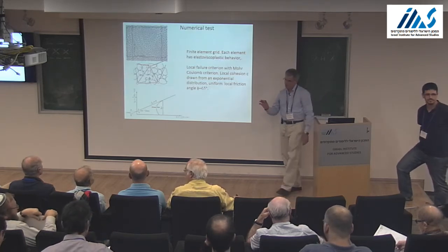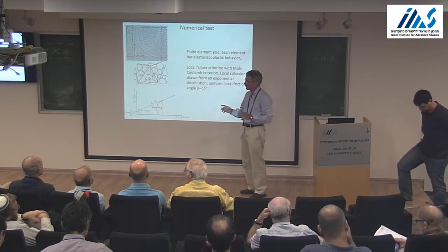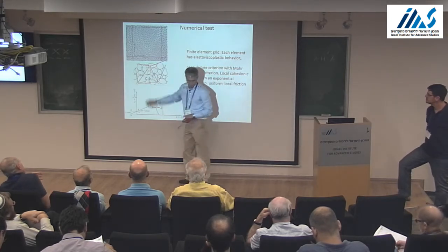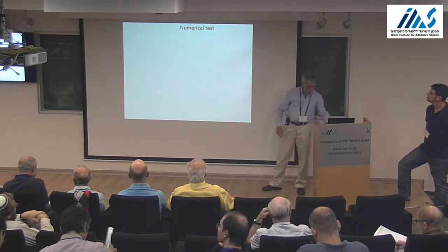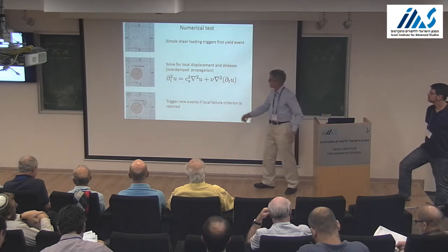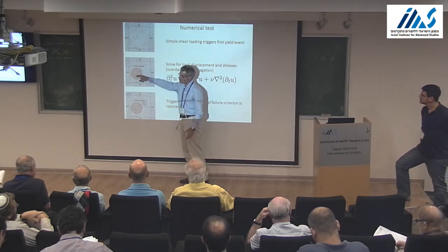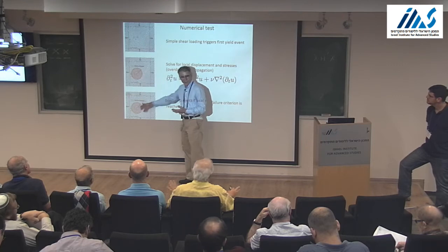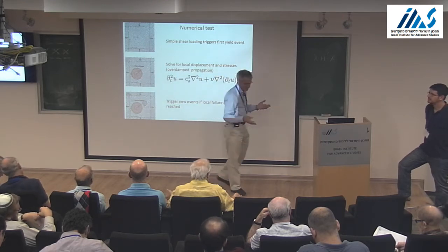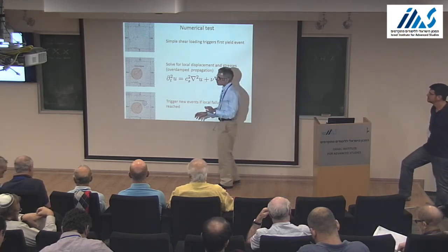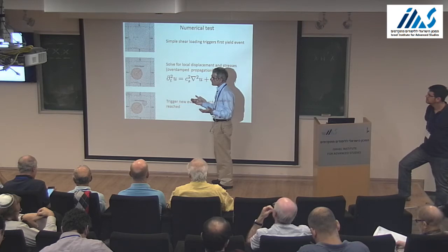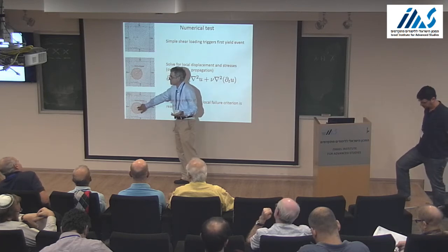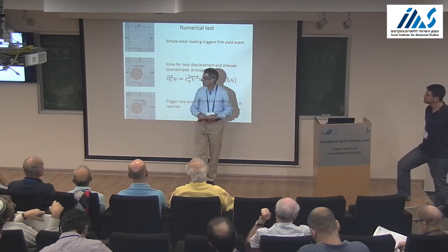I agree with that, but there is one issue that was also raised in a question to Alan Nidelman. When you have a shear transformation operating, the inclusion, when it is yielding, is not elastic anymore. It's more like viscous. So if you have many of them, you can question that. If you use an elastic propagator, this is an issue. If you use finite elements, by construction you are taking this into account. This finite element is not treated as an elastic medium.